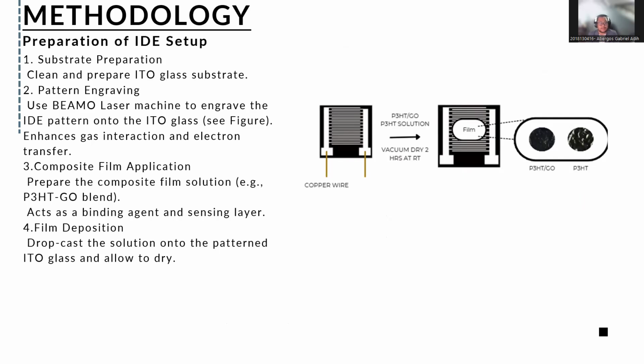Next is the composite film application, the preparation of the composite film solution, which is the P3HT-GO blend, and acts as a binding agent for the gas sensing layer. Then for the film deposition, the solution will be drop casted onto the patterned IDE glass and allowed to dry.